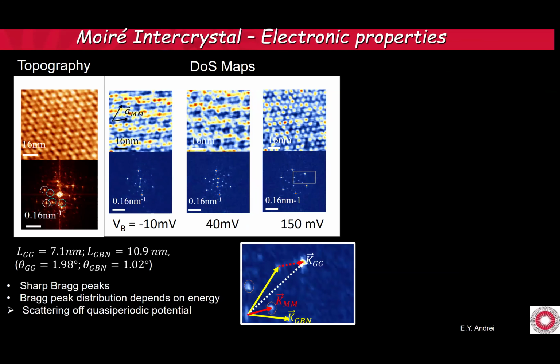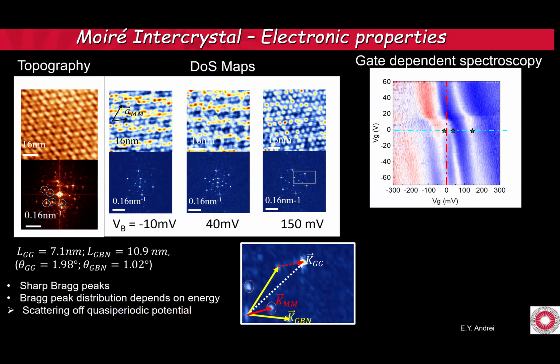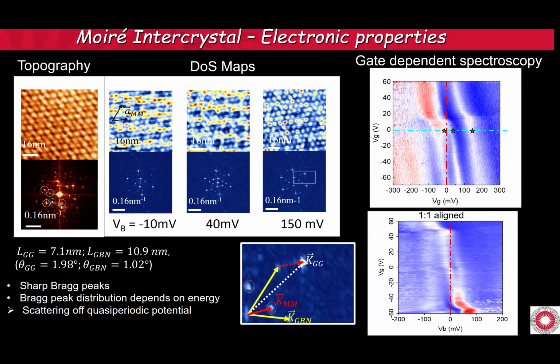Now let's go to an incommensurate crystal. So this one is 1.98 degrees and 1.02 degrees. And now what you see is at every energy, the Bragg peaks are different. So they light up and they get darker. And I'm going to show you a movie. So these are our 4 lattice vectors. And this is now the density of states map. And you see it's very different from the one where it was one-to-one aligned. Extremely, completely different. It's unrecognizable, but we still open a gap at the Fermi level. And here it's actually an even larger gap.